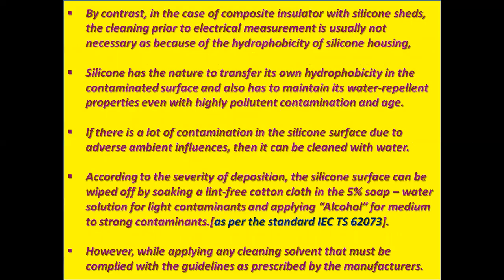By contrast, in the case of composite insulator with silicone sheds, the cleaning prior to electrical measurement is usually not necessary because of the hydrophobicity of the silicone housing. Silicone is such a material whose hydrophobicity is much higher. Silicone has the nature to transfer its own hydrophobicity to the contaminated surface and also maintains its water repellent properties even with highly polluted contamination and age.